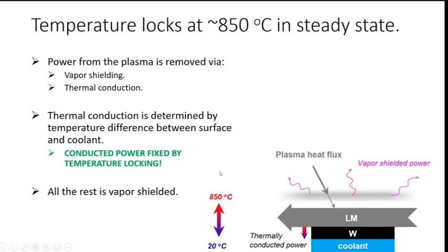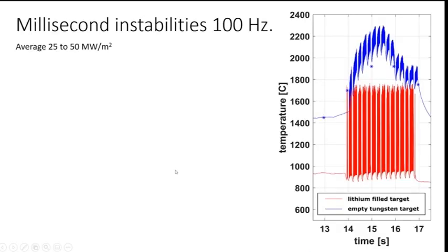So let's take a look at some pulses. We know this works in steady state, but what happens during a pulse? And as I said, Magnum can do this quite well. And what we have done here is the most severe loading that we ever did on a sample like this, which is instabilities of 1 millisecond each applied at 100 Hertz. And if you see here, I noted in green that each of these little peaks is actually about 15 pulses that are so close together that you cannot discern them in this figure.